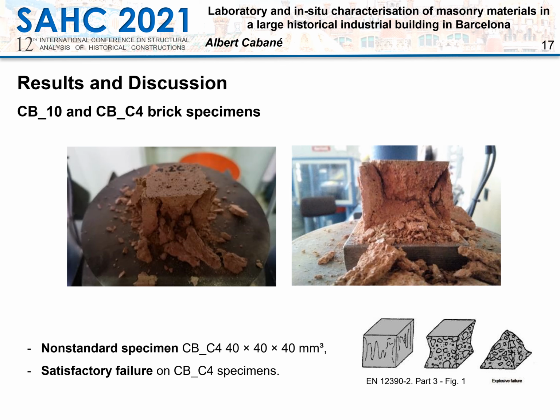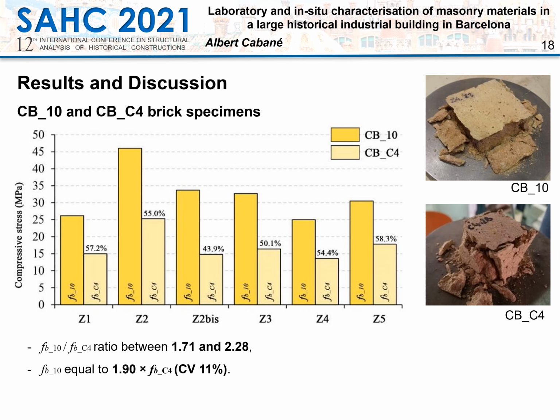Furthermore, this proposed specimen has shown satisfactory coefficients of variation in its strength average, similar to those obtained with the standard specimens. Now, we can see the relationship between the experimental compressive strength obtained on standard and non-standard specimens. This comparison makes it possible to observe that the average compressive strength obtained in the non-standard specimens represents between 44% and 58%. This represents an average relationship of 1.9 between the compressive strength obtained with the standard and the non-standard specimen.